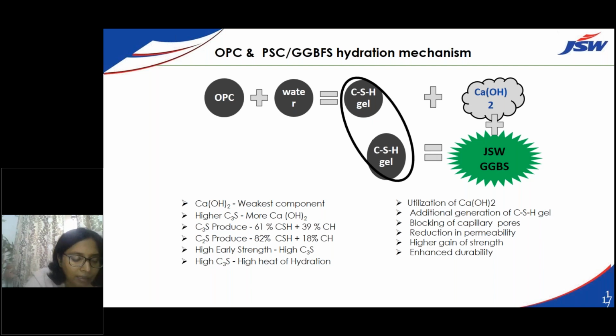We are adding slag. So slag reacts with calcium hydroxide to form another layer of calcium silicate hydrate gel or tobermorite gel. So this gel is very good, and this is going to utilize all the calcium hydroxide in the system. It blocks all the capillary pores. It reduces permeability. With reduction of permeability, there is also a high gain of strength, and the durability of the structure obviously increases.